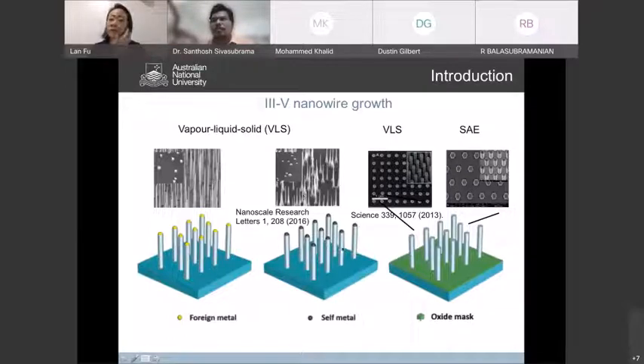Obviously, if you put metal onto the substrate, you introduce foreign impurities into your material, and sometimes that could be detrimental or very bad for your device performance. So people have also demonstrated using a self-metal, the constituent metal of the material such as gallium. By tailoring your growth conditions, you can form droplets of your self-metal at the beginning of the growth and use that to promote nanowire growth through this VLS technique. But as you can see, with those techniques you have a really random distribution of nanowires on your sample, which is not very desirable for a lot of device applications.